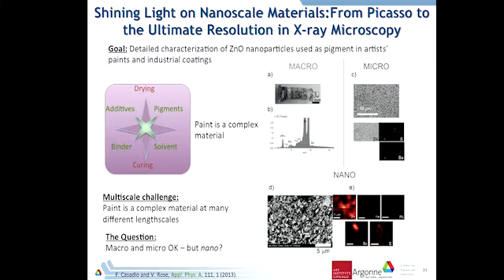At the microscopic scale, well, you might look at what the paint looks like. You get the little flakes of paint, and you can analyze those flakes. But it turns out that in order to actually distinguish the different paints, you have to go much smaller than the microscale. You have to go down to the nanoscale. And so what we did was use a technique called X-ray fluorescence, which will tell you not only what elements are present, but also how they're distributed in a piece of material. And we use that to look at the paint flakes.